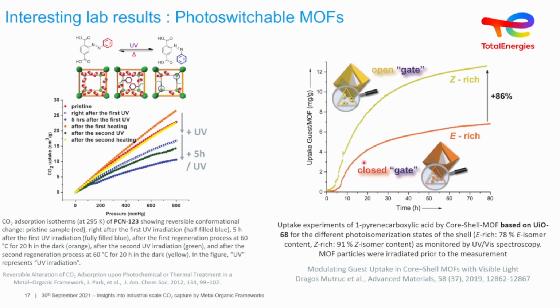More recent results are not with CO2, but again, these gate opening and gate closing effects here. And this is carried out in the liquid phase with this pyrene carboxylic acid. But I think it's very interesting to see these different types of materials and these types of opening and closing. So I think quite nice. The other thing that I think is nice here is that they looked at core shell MOFs. And this again is something that could be of interest if we can make them at a large scale.